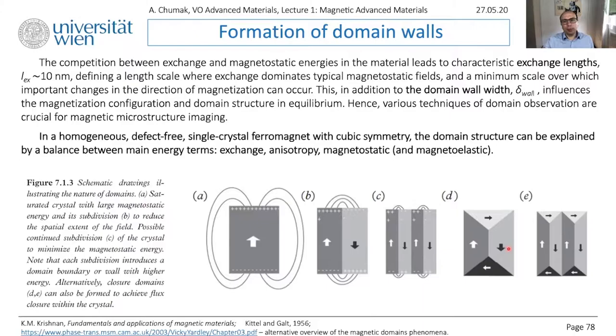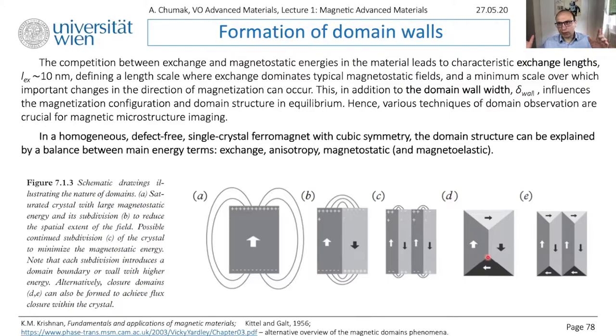This we already discussed a little bit. What's new here is that the minimum of energy requires us to take into account exchange, magnetostatic (dipolar stray field), and in addition there is crystallographic anisotropy, which I mentioned several times during the lecture course. All of these should be taken into account — the total energy should be minimized. What is often studied nowadays is the domain wall — a region between two domains — because exchange interaction tries to make the domain wall as wide as possible so the angle between neighboring spins is as parallel as possible, while dipolar and anisotropy energies want to make it small.